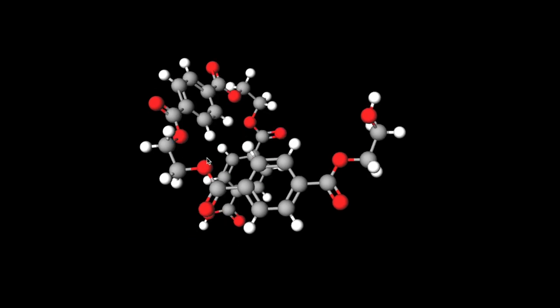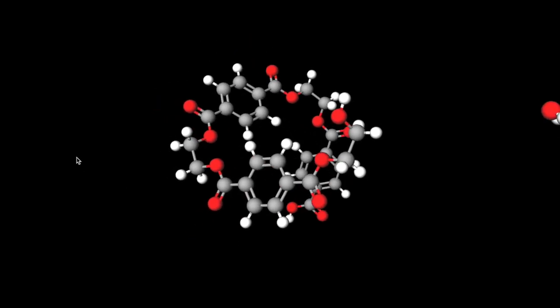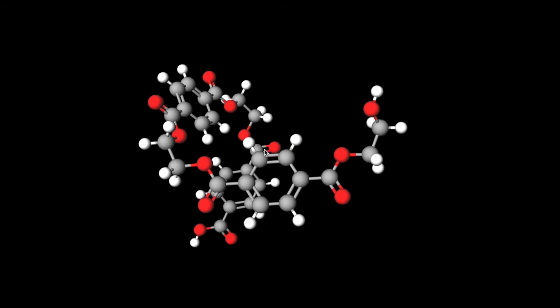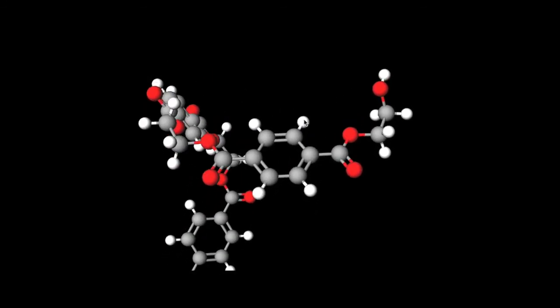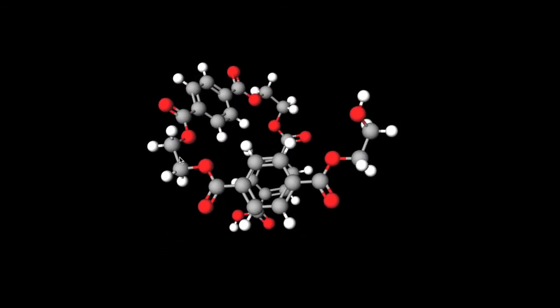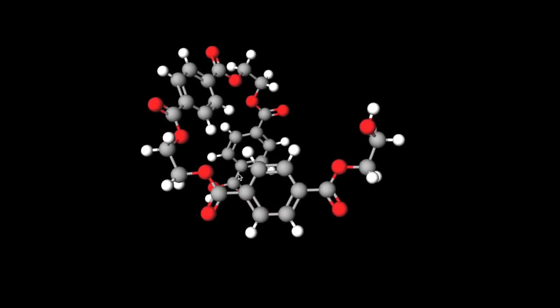The ball and stick models also illustrate that the PET molecules aren't straight, they are quite curly and wavy. This makes PET usually amorphous in structure and consequently clear.